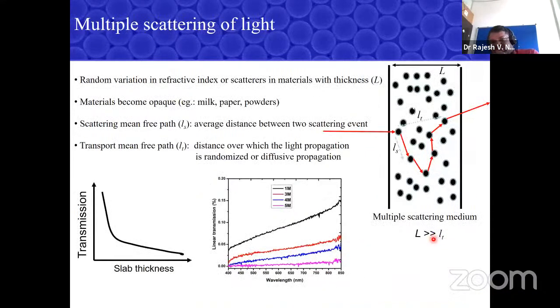So before I get into my experiments, when you talk about disordered samples, when light enters a disordered medium, when I say disorder, please understand it means a disorder in dielectric constant. In all the previous slides, the scatterers have definite positions and I can have a definite periodicity. But in a disordered medium, the systems are quite scrambled and random, so I don't have any spatial periodicity in the system. Okay, white paper, milk, powders, a chalk powder in your class, these are all nice disordered systems. And if you increase the disorder or the thickness of the sample, the transmission drops down because light is getting multiply scattered.